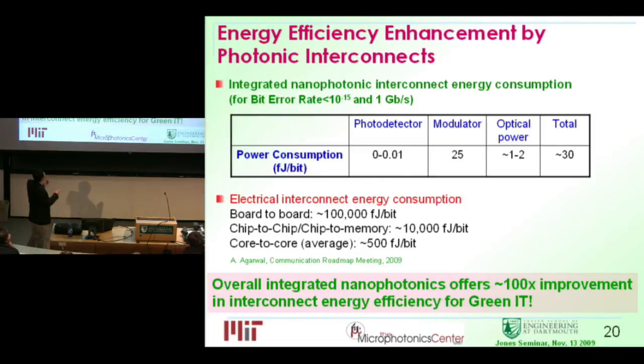So as I promised, we can figure out the power consumption to transmit 1 bit of data with the photonic approach. Photodetectors consume practically almost zero power because they operate in photovoltaic mode. The modulator is about 25 femtojoules per bit. The optical power used for a bit error rate of 10 to the minus 15 is determined by the performance of your photodetector. You calculate this, along with all the loss from the modulator and waveguide and the efficiency of the laser. You still only consume 1 to 2 femtojoules per bit. So adding them together is about 30.